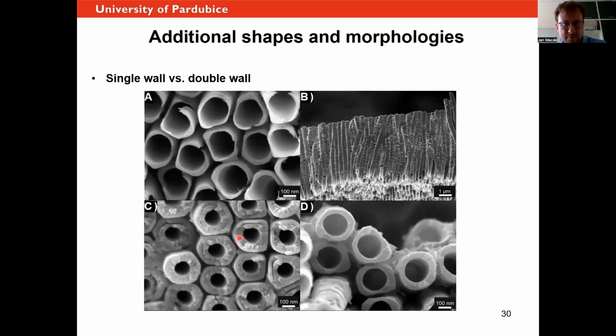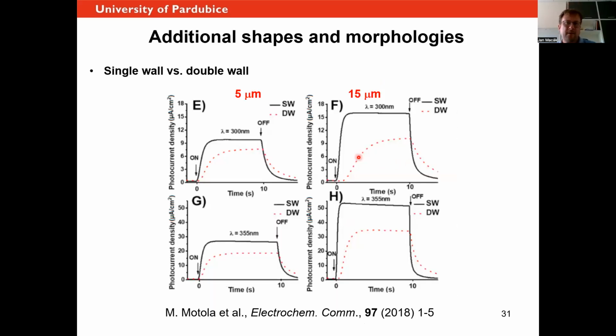So this is a typical example of the double wall structure. So you see the porous wall, that is etched, actually the outer wall, and after etching everything's clean. This double wall structure has some implication on the photocurrents, because we shouldn't forget the TiO2 is a semiconductor. So if you do photocurrent measurements, you will see that the single walls actually achieve usually slightly higher photocurrent density than the double walls, because there is simply more pure TiO2 overall than with the double wall morphology. Also the onset, so the speed with which the photocurrent reacts, is faster. And this applies also for tubes of different thicknesses.